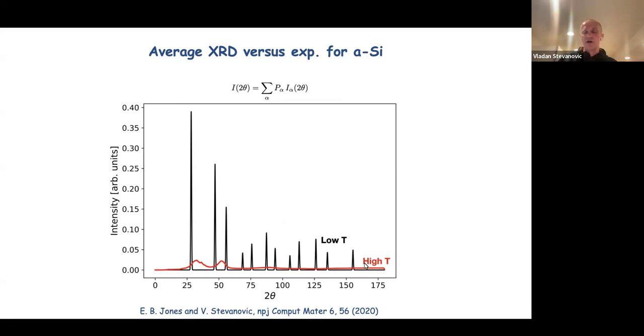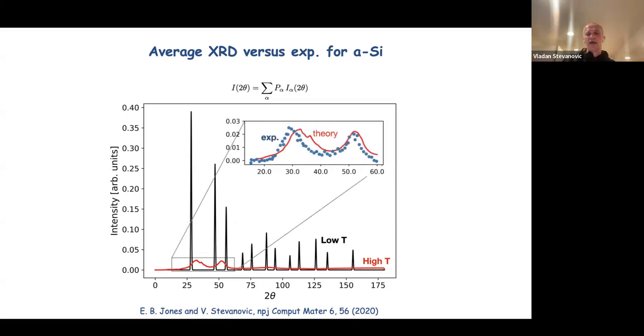And at high temperature, you find this mixed phase, where now all these X-ray diffraction patterns are mixed together. And of course, the long range order will melt. What you will find are these broad humps in the average X-ray diffraction pattern. So what we did is go into the literature looking for X-ray diffraction data on amorphous silicon. We do indeed find these two broad features that have been identified experimentally, and the correspondence between what we find and what experiment finds is, in my view, fairly good.